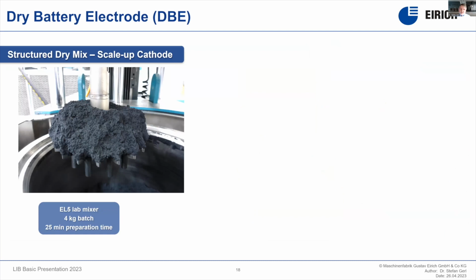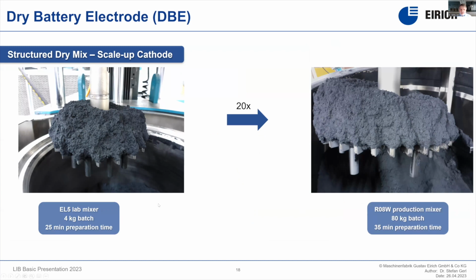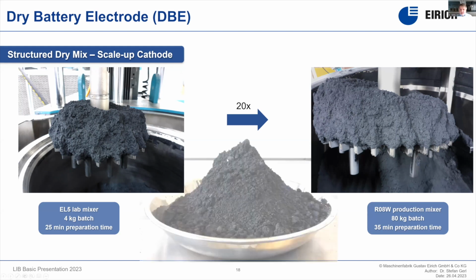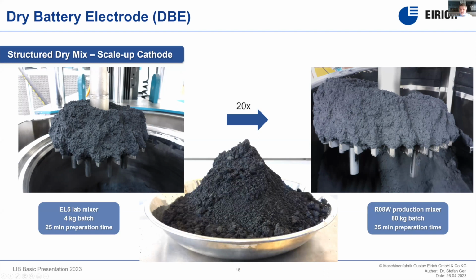Customers, of course, are asking whether this is not only possible in lab scale, but also in large scale. So we have performed several times for customers already scale-up trials onto our 75-liter machine. This means from a 4-kilo batch up to an 80-kilo batch. We prolonged the mixing time a little bit because the cooling takes a little bit more time in a bigger machine than in a smaller machine. But at the end, we are ending up with exactly the same material properties.